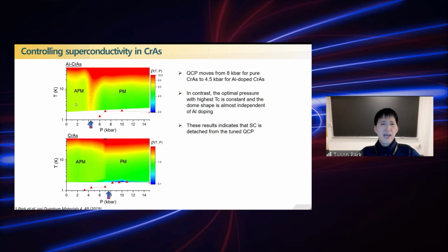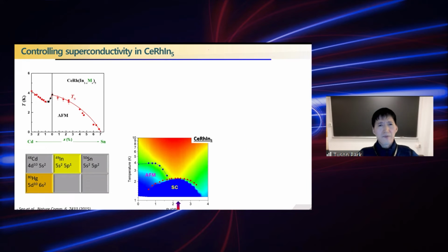Yet the dome of superconductivity did not change much. If you did not see this, then you may argue that superconductivity arises from the quantum critical point. But by performing this experiment, we can clearly say that superconductivity is accidentally located in the vicinity of the QCP in chromium arsenide. How about in the heavy fermion compound, CeRhIn5?